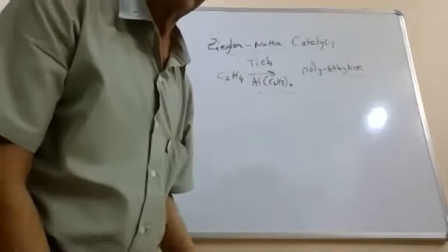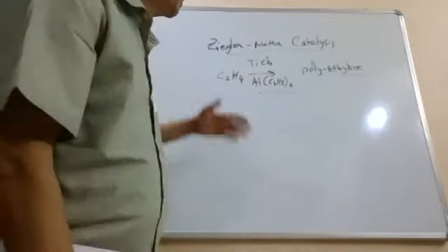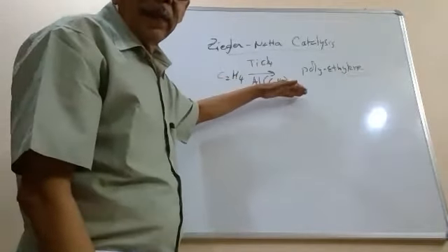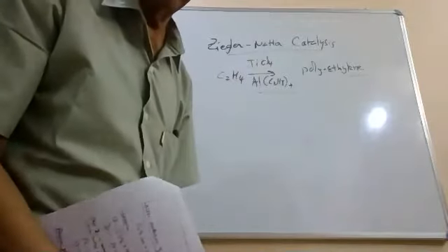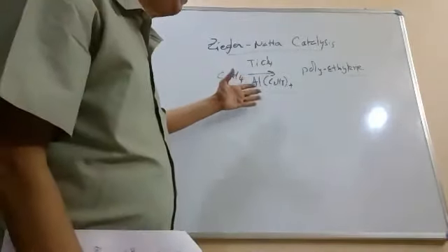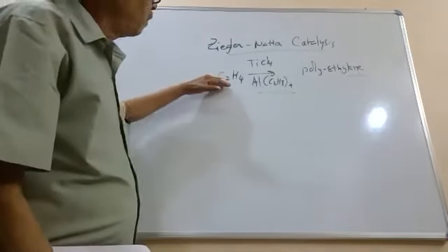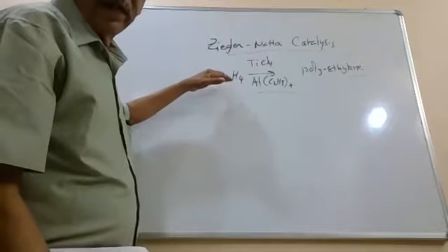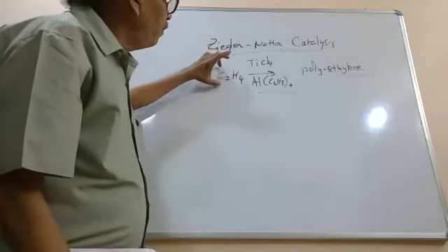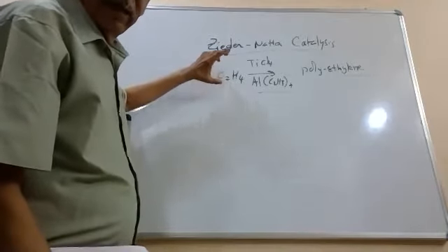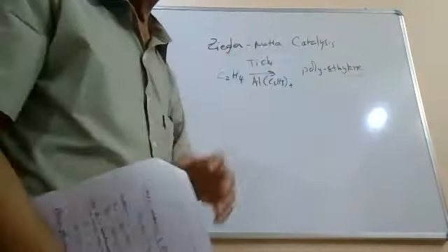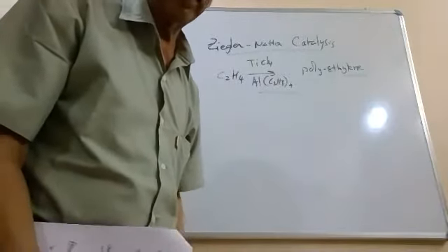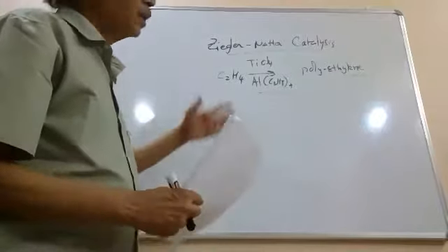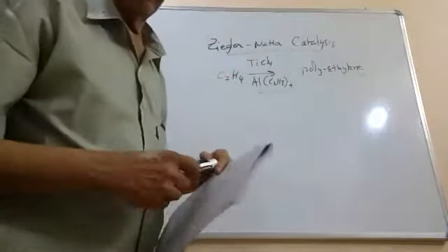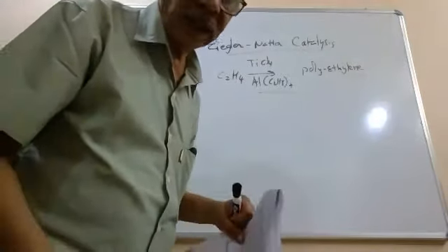This is a very important transformation, the polymerization initiated by the presence of titanium and aluminum here. And if you change the titanium to tin or the aluminum to silicon, the reaction won't work. This is a very specific combination, and it has a lot of commercial importance because polyethylene is used in a variety of applications in society. And this gives you a very stereo-specific polymerization. Not only ethylene, you can also use dichloroethylene or chlorobromoethylenes. So you can modify the reactant molecule in different ways, and most of the time you end up with a very stereo-specific polymer. This is of extreme industrial importance, so you should be aware of it. And Ziegler-Natta got the Nobel Prize for the discovery of this very important material.